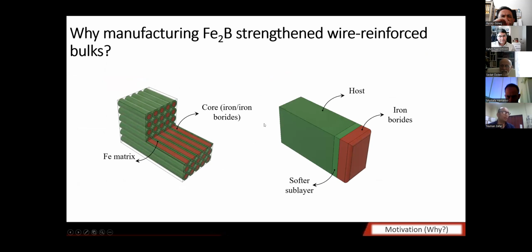One might ask, why go through all this trouble and not just surface boride the material? The surface boriding of steel is used only for corrosion and wear resistance in aggressive environments. And mostly, because you have a lot of wanted and unwanted elements in the steel, whenever you apply surface boriding on the steel, a softer sublayer is formed under the borided layer. In this approach, we don't believe something like this will happen.